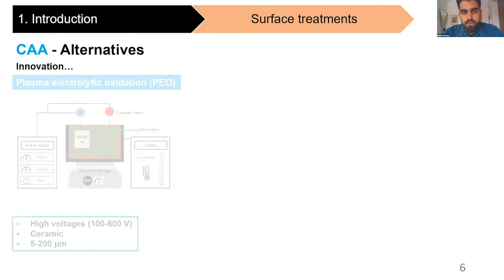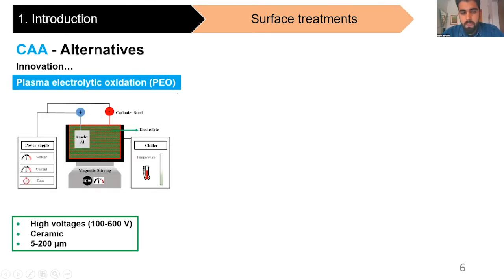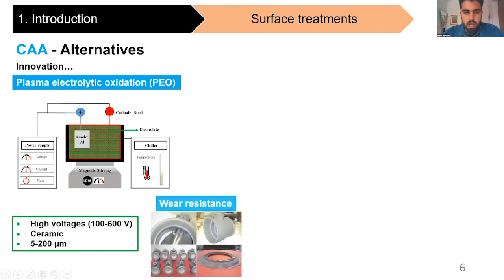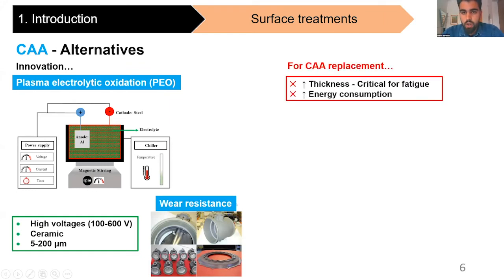An innovative alternative is plasma electrolytic oxidation, PEO, which is an electrochemical treatment characterized by the use of high voltages and long treatment times, and gives rise to the formation of ceramic coatings with thickness between 5 and 200 micrometers. This is conventionally useful for wear-sensitive applications in the aircraft industry. However, for chromic acid anodizing replacement, this high thickness value is critical for fatigue-sensitive components, and the inherent condition of this process involves high energy consumption.